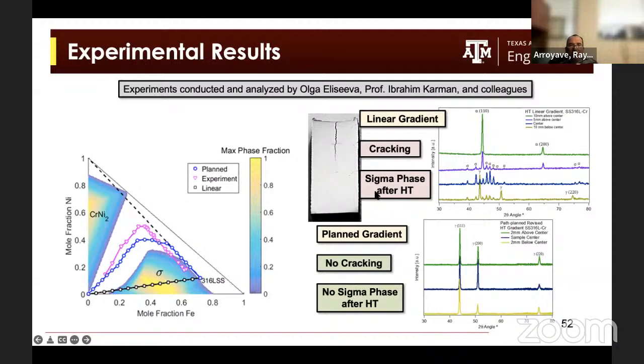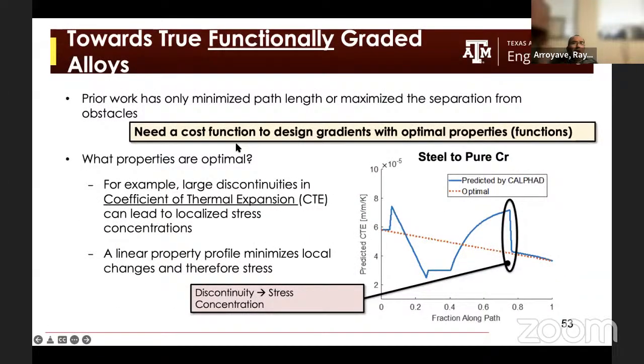We were able to see a compositionally graded path that had no cracking, and we didn't observe any sigma phase even after heat treatment under temperature conditions where the sigma phase would be observed if you actually had a composition in this region where you have sigma phase. Now, we have demonstrated that we're able to optimize a path by avoiding obstacles.